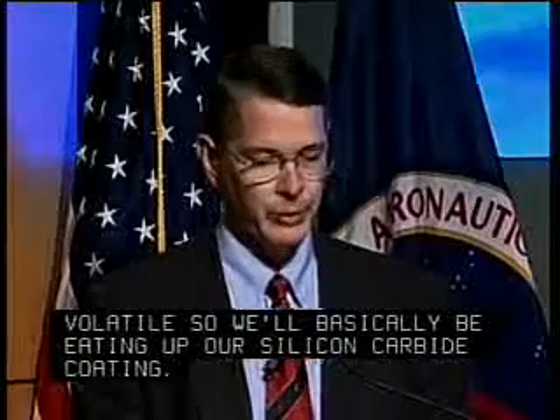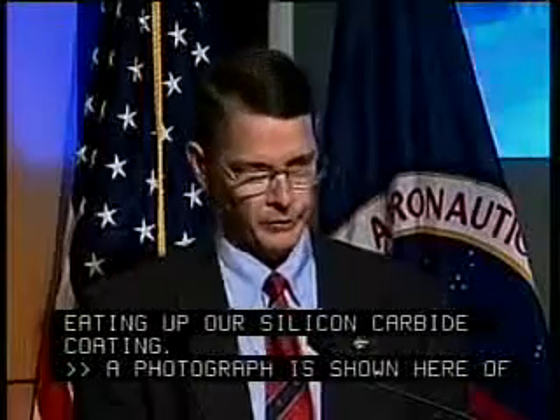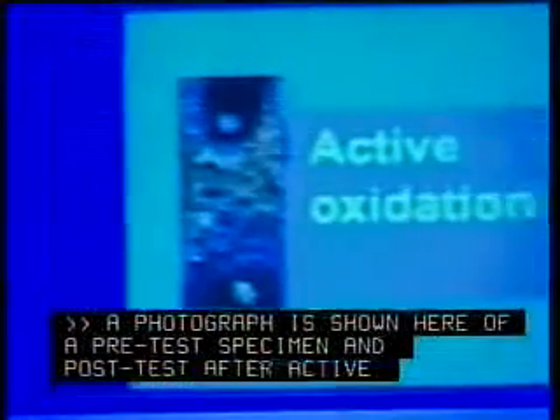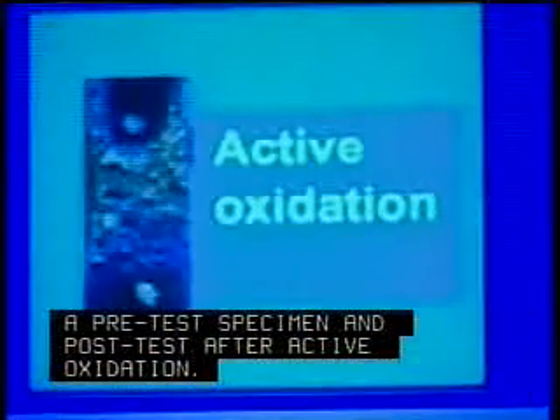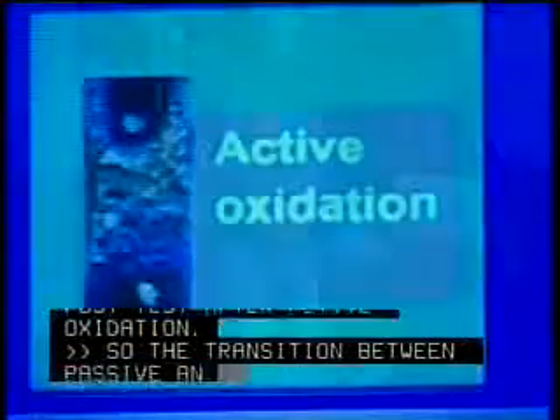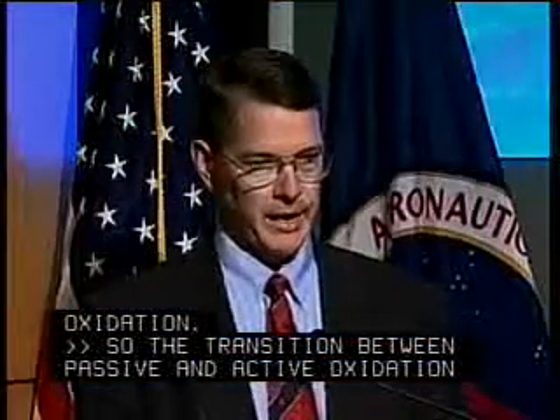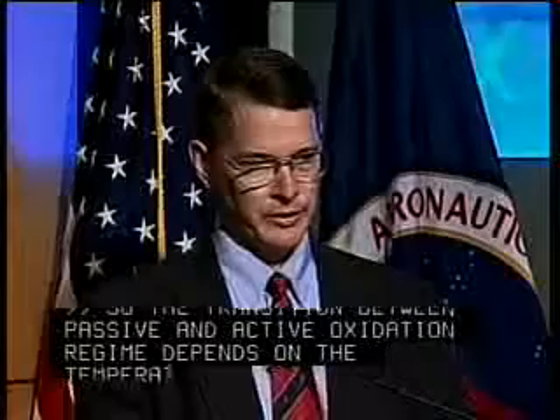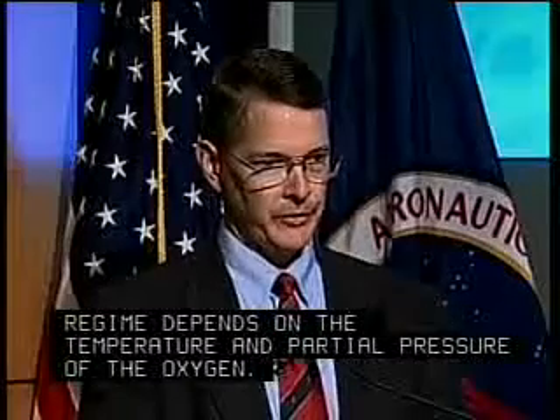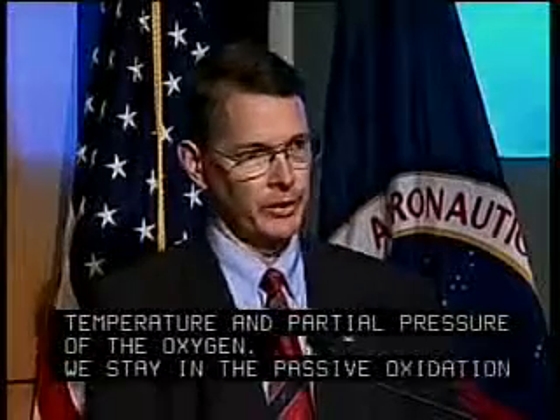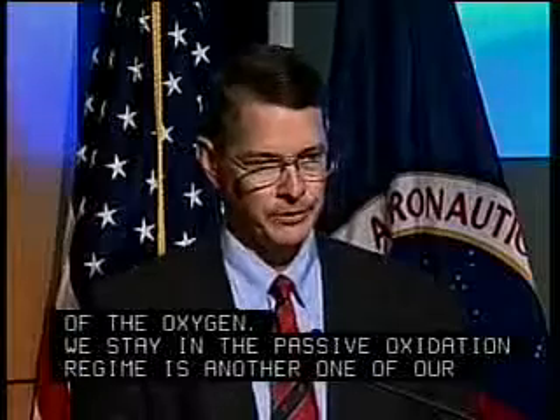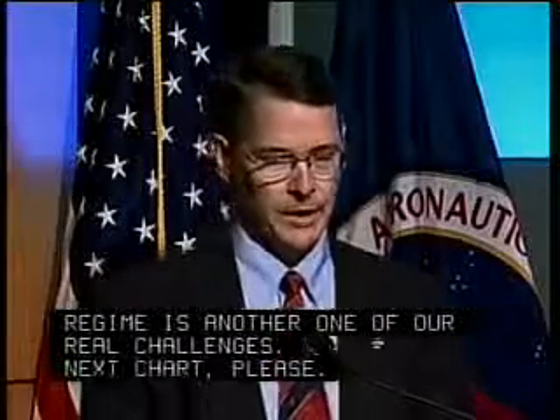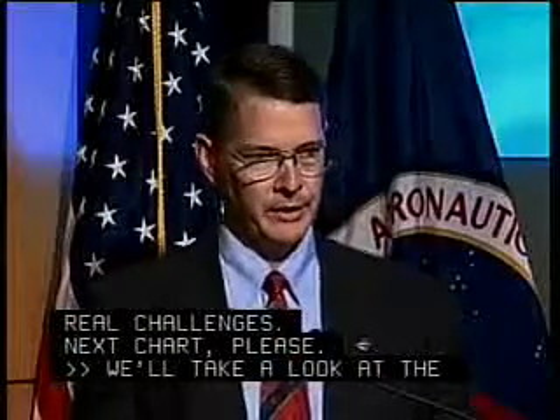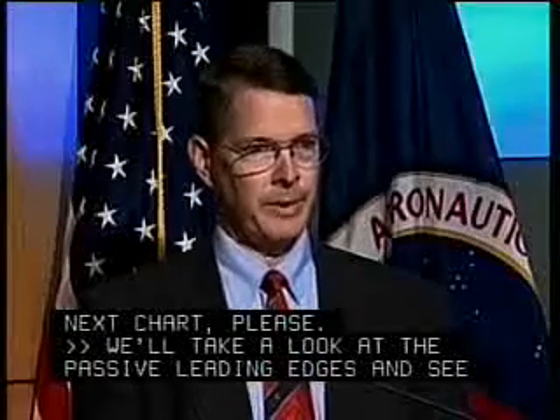A photograph is shown here of a pre-test specimen with silicon carbide coating and post-test after active oxidation. So the transition between passive and active oxidation regime depends on the temperature and partial pressure of the oxygen. And staying in the passive oxidation regime is another one of our real challenges. Next chart, please.